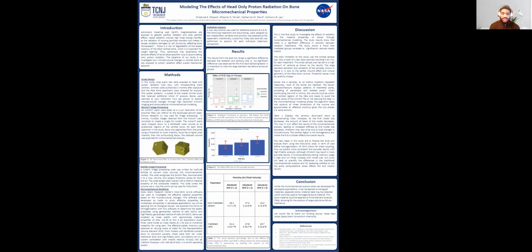It was traditionally used to calculate the mechanical properties of composites used in aerospace, but it can be adapted for biological tissues. The software ran numerical simulations to determine the effective elastic properties of composites by assigning material properties to each subcell. Traditionally, finite element analysis has been used to define structural integrity, but GMC is better at computing the material properties of bone since it relies on details of the microstructure, while finite element relies on the overall geometry.